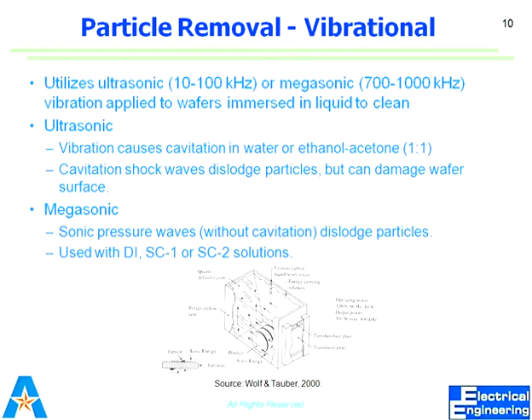In that liquid, we produce those sound waves, and due to those sound waves, the cavitation effect comes into account, and the particles on the surface of the wafer get displaced, and because they are moving, the wafer surface can be cleaned. But you know that due to this cavitation shock, because the bubble collapsed suddenly, it works like a shock. Due to this cavitation shock, the wafer surface can be damaged as well. So just to avoid this cavitation shock, we go to higher frequencies, we go to megasonic frequencies.